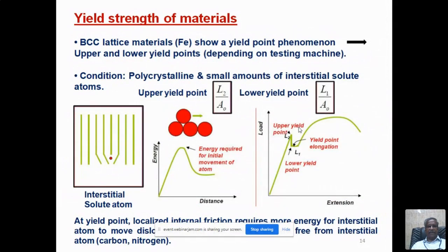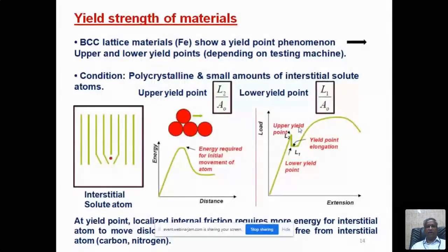The yield strength of the material is also affected by a yield point phenomenon. It is a big phenomenon especially in BCC materials. As I told you in the beginning, in the third graph, the stress-strain curve, they have mentioned that yield point elongation is taking place. There is a jerk when you measure the load-displacement graph or stress-strain graph. You will find a small change in the slope of the curve. That point is where yielding starts. This type of phenomenon occurs only in a few materials, not in all materials.